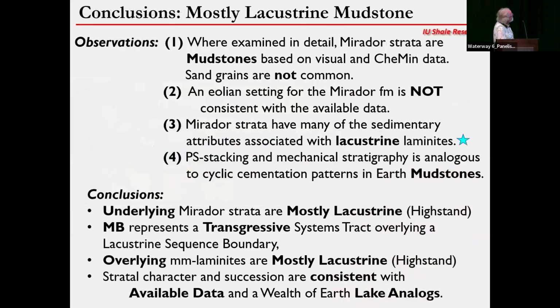So in conclusion, we think it's mostly lacustrine mudstone in that succession instead of sandstones. Because when we examine in detail, based on visual and CheMin data, sand grains are not common. And the aeolian setting for the Mirador formation is not consistent with available data, at least not the prevalent aeolian setting. The Mirador strata have many of the sedimentary attributes associated with lacustrine laminites, and the parasequence stacking and mechanical stratigraphy is analogous to cyclic cementation patterns in mudstones.